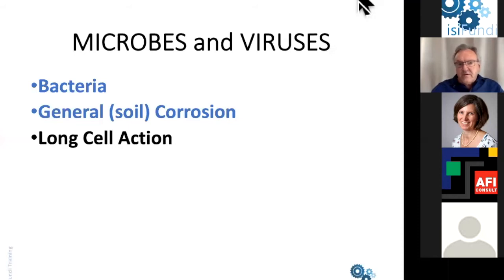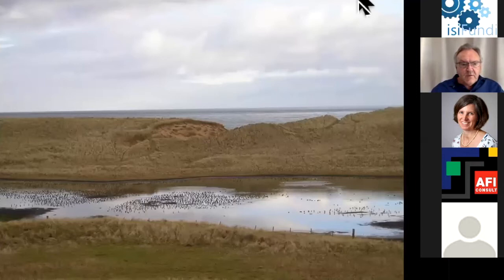When we get different soils, we then get what we call a long cell. So here we have a situation where there are pipelines which traverse from the position of the photographer across that loch. This picture actually comes from Scotland, through the dunes and into the sea. So you can see that we have 4 different environments in that situation. And depending on the characteristics of those environments, we can get certain areas of the pipeline being anodic, others being cathodic, and corrosion of the pipeline occurs in the anodic areas.